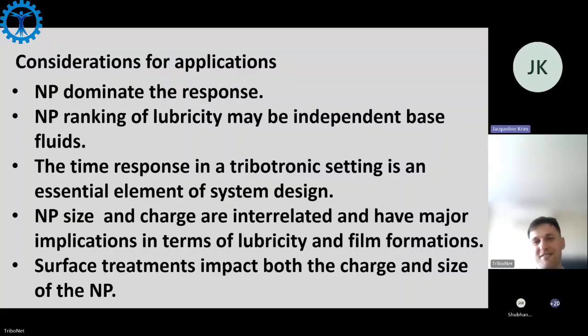The nanoparticle size and charge are very interrelated. They have major impact on lubricity. What's kind of interesting is when you put the surface treatment on, it changes the size of the nanoparticle and it changes the charge. So if you have one treatment on one core particle and a different treatment on a different core particle, you end up with very different size and charge. So it should be no surprise that they behave differently. Okay, next slide.